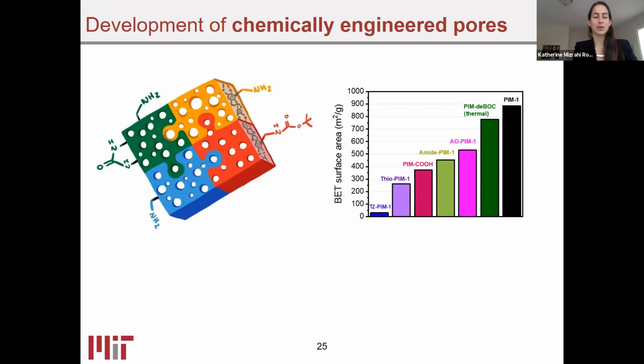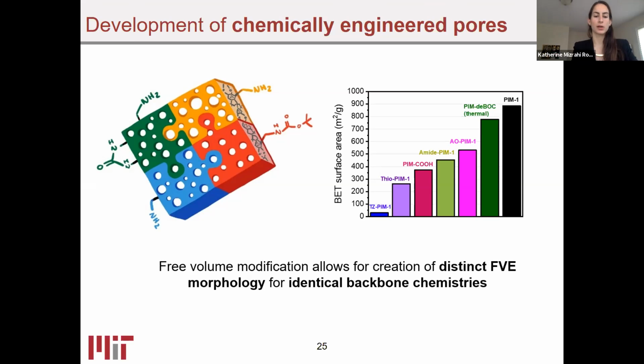Having done this study, we were really excited to find that we could chemically engineer pores, that free volume modification could allow us to create distinct free volume element morphology in these samples for identical backbone chemistries. As you can see in the schematic on the left, it's a puzzle piece built from the exact same backbone, but slight changes in either the processing or the chemical structure of the sample can result in really large differences in performance. One really encouraging aspect that we also found is that the BET surface area of the thermally deprotected sample was very close to that of PIM1 and higher than many of the other functionalized PIMs that we had seen in the literature, which indicates that this can be a really promising method for tuning the porosity of the sample and enhancing performance in materials that initially may not show such promising performance.